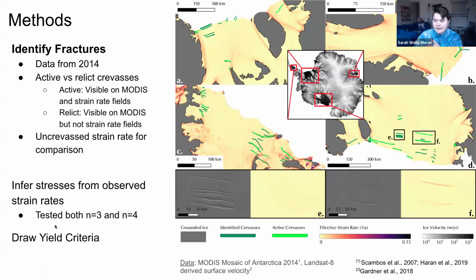Yeah, so we were using Landsat 8 derived surface velocity from Gardner et al., but didn't test between various velocities. So that could be a very interesting future direction. Another thing that I was thinking about in preparing this presentation is that this is all 2014 data, and potentially looking at Sentinel-1 derived velocities on specific ice shelves and specific areas could help suss out some of these uncertainties of having just the one time frame. This was more of a broad, all of Antarctica assessment of fractures, but we also had 36 total fractures that we were able to identify on both strain rate and optical imagery. So could definitely use another person going through and doing this in specific areas, especially.